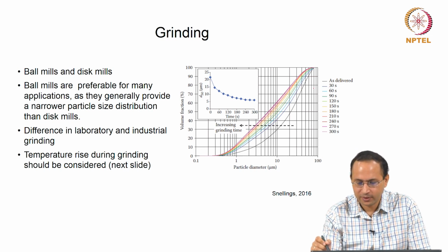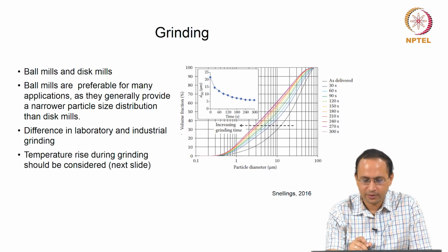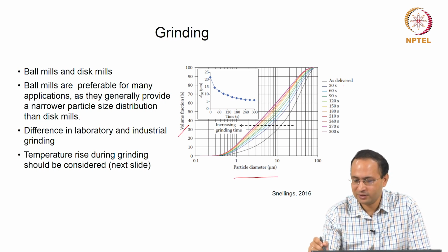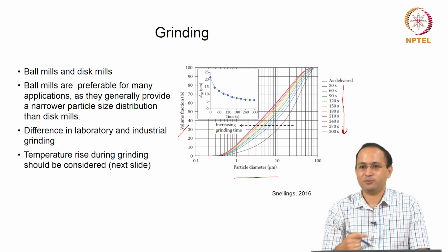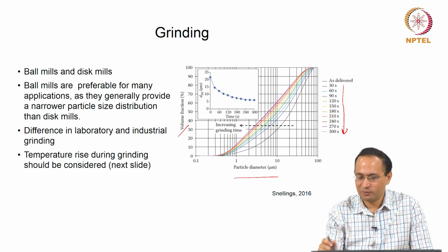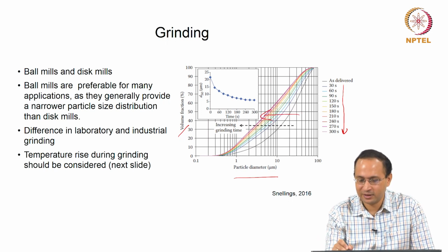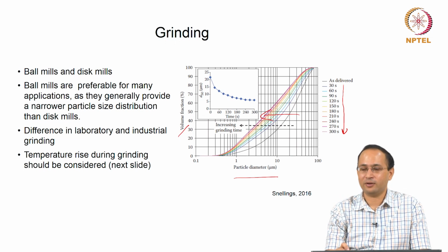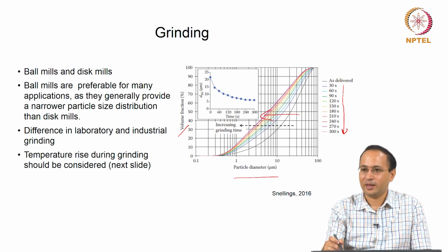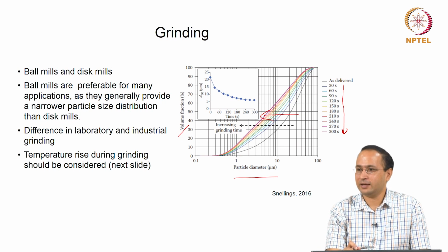Here you see a plot of volume fraction versus particle diameter. What you see here is the effect of grinding time, so 30 seconds to 300 seconds. If you are grinding for 300 seconds, what will happen? You are basically shifting the curves this way. You are making your powder finer, right. So these are the things you have to always keep in mind. Suppose you adopt different grinding times for your samples, that will affect your properties, right.